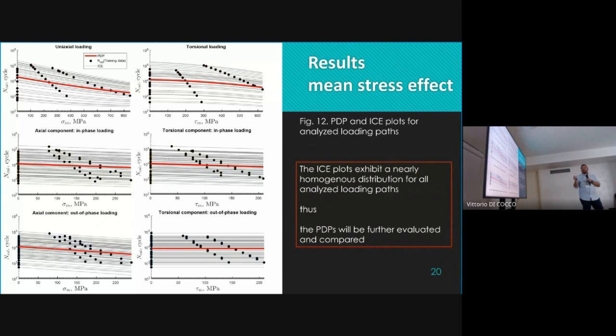For the in-phase loadings, you can see this. We can see the impact. Obviously, the values are quite lower. I would like to point out that we get up to 280 megapascals compared to 800 on the top. There is an impact, but it's somewhat equal between axial and torsional stresses. It lowers, right? But it lowers roughly the same for both of them.